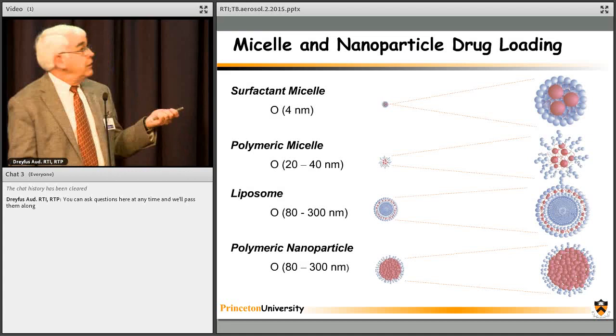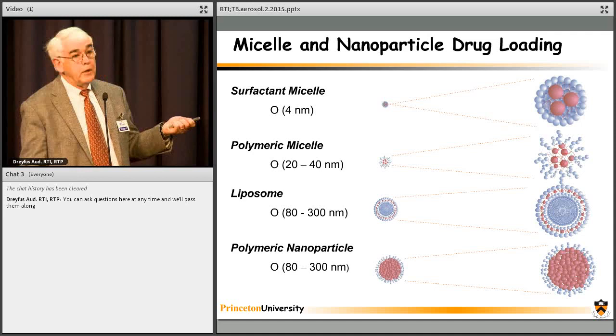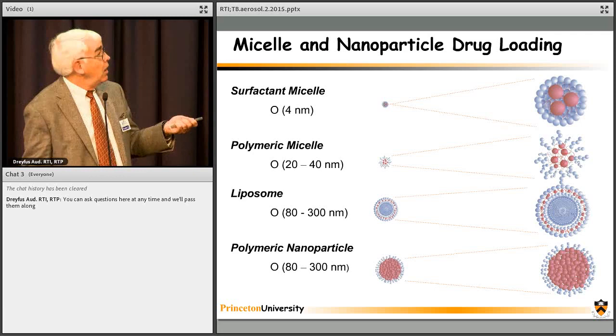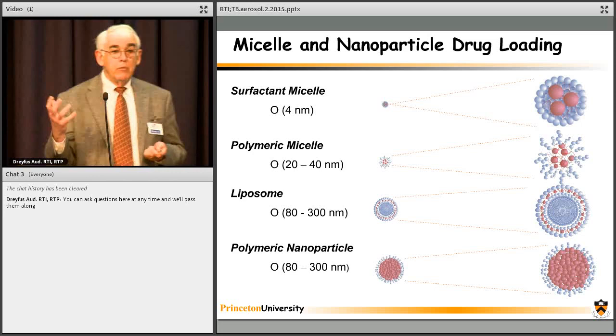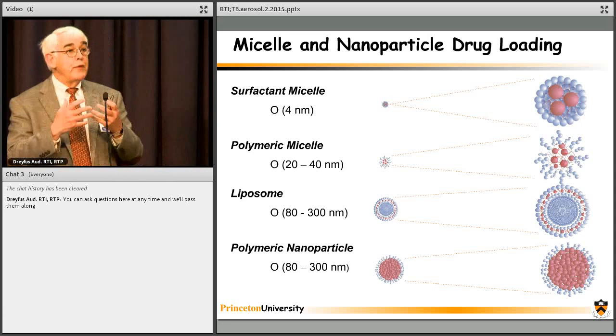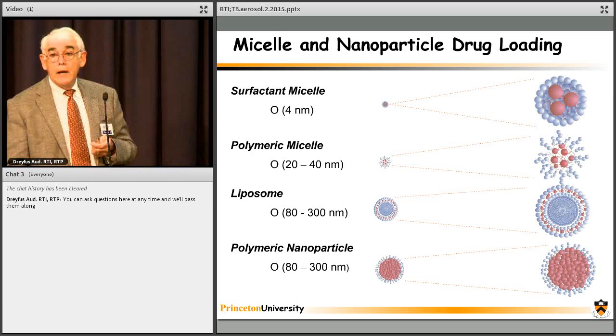Surfactant micelles, and these are all drawn to size scale here. So a surfactant micelle, whether it's a non-ionic surfactant or an SDS molecule, is about 4 nanometers in size. The red with a paclitaxel molecule, that's the size scale of that relative to micelles. You can fit a couple of paclitaxel molecules, an anti-cancer drug, in a micelle. However, the surfactants are partitioning on and off of that on microsecond timescales, and so the paclitaxel is not really protected in any sense. The micelle is a dynamic object.